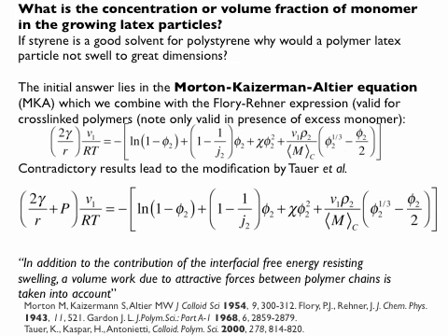So you have in a way 3 terms here. The first 2 are the entropic contribution towards mixing. The one in the middle is the Flory-Huggins interaction parameter, which says something about the enthalpic contributions. So is there a positive interaction between the polymer and the monomer, or a negative interaction?